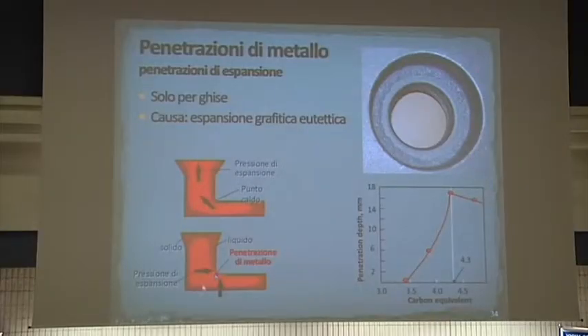And here is an example of the way we understand expansion penetration. You can see it here. That's a case of expansion penetration. So what happens, for example, in this casting, as solidification proceeds and you have graphite expansion, the metal is pushed out to the riser. But if you have a hot spot here, you are going to still have liquid metal here at the corner. And then if the riser has been closed and you still have expansion, the metal is pushed in the mold. So that's expansion penetration. So the solution to that is the way you design your mold and gating system.